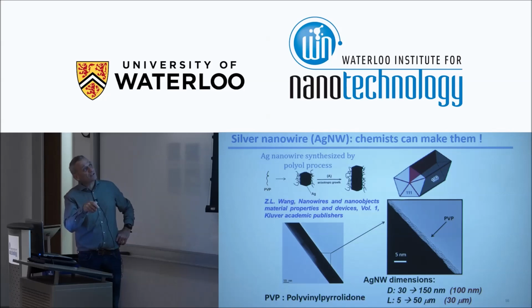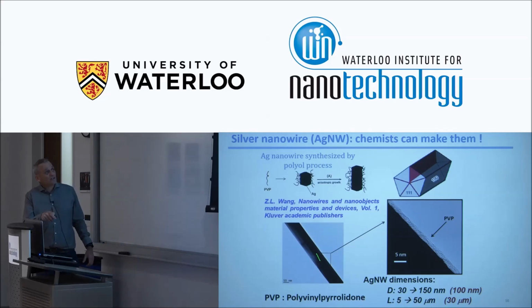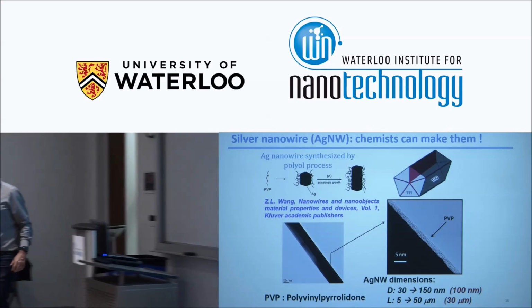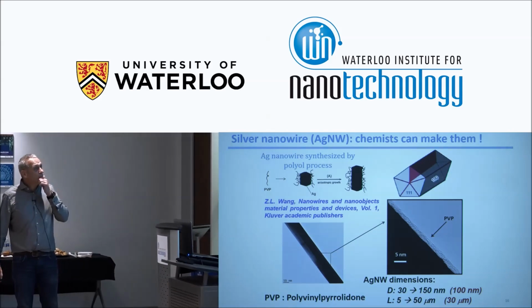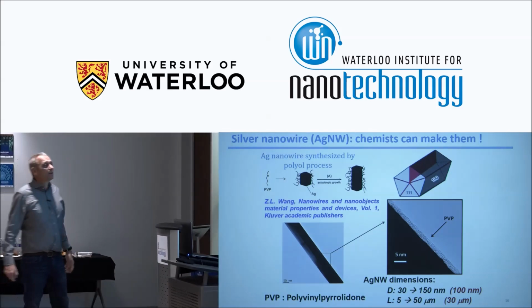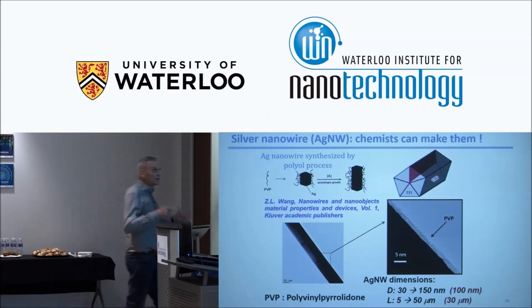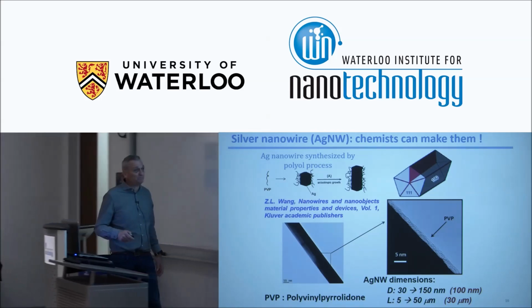So we have a 5-fold symmetry with some twins. We have long 100 planes, which are covered by PVP, and the 111 faces at both ends, which are free. If we make a TEM picture here, the scale is 50 nanometers. We have very long nanowires. If we make a zoom here, we have silver, the vacuum, and here a thin layer of PVP that is 3-4 nanometers, which has been used to help the one-dimensional growth, preventing the lateral growth to occur.